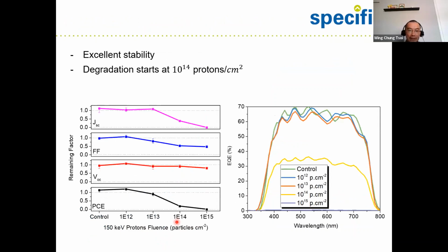Then we plot a graph of the remaining factor of the device parameters against the proton fluences. You can see the power conversion efficiency is basically maintained, quite similar to the control device, up to 10 to the power 13 protons per centimeter square. And then it starts to degrade. If we look at the device parameters, it's mainly due to the short circuit current density and the fill factor, which drop quite significantly at high fluences.